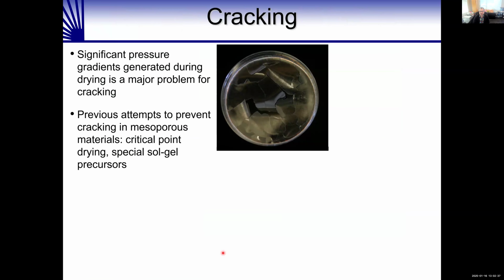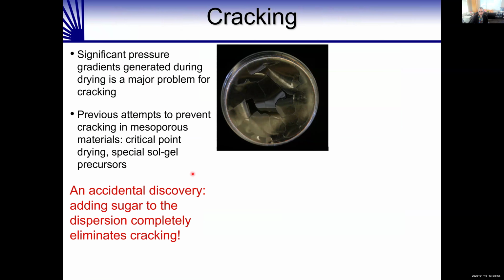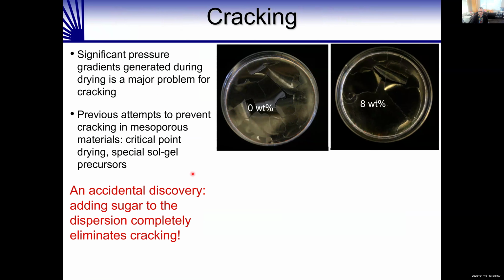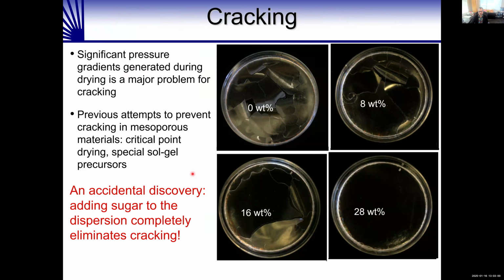But we made an accidental discovery several years ago that allowed us to make much larger films without cracking. The problem is that as the films dry, pressure gradients develop and lead to cracking. So what we discovered was that if you add sugar to the sample before it dries, you can completely eliminate the cracking. These samples show no sugar added, 8 weight percent, 16, and 28 weight percent. After 28 weight percent, we get a large crack-free film.